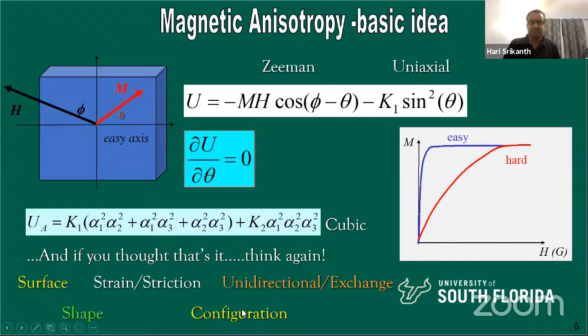Configuration, you can make nanoparticle clusters, and these clusters are attached to each other. You can make them in different sizes and shapes and configurations. So that can be used for playing with the anisotropy. And last but not the least is this exchange anisotropy or unidirectional anisotropy. Now, when you hear of exchange bias, this is something very important for the spintronics community. Those that work in magnetic materials, MRAMs, spintronic devices, for example, one of the critical properties is the interface between a ferromagnet and an antiferromagnet, okay?